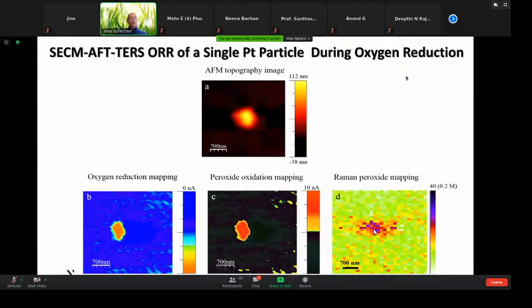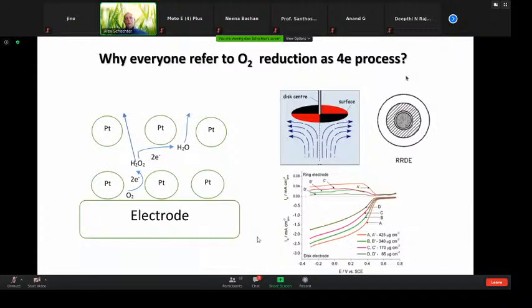Here the resolution is less observed, but indeed we were able to show the same behavior. So what did we understand from that? We understand that everyone else thinks that platinum is a 4 electron reduction catalyst. It takes oxygen, 4 electrons, 4 protons, and directly transforms it into water. While in our case, we measured and we saw that most of the current is assigned to peroxide formation, to the 2 electrons, 2 protons, and then peroxide, and then peroxide into water.